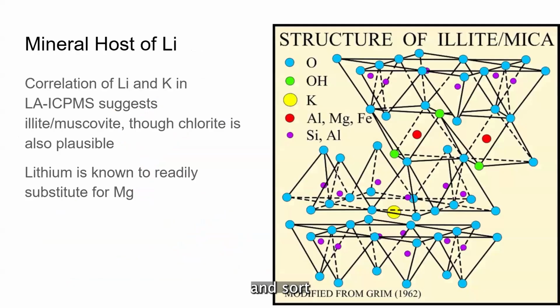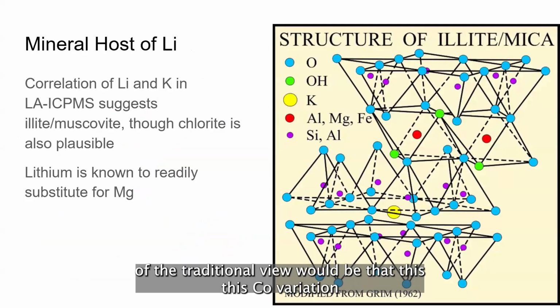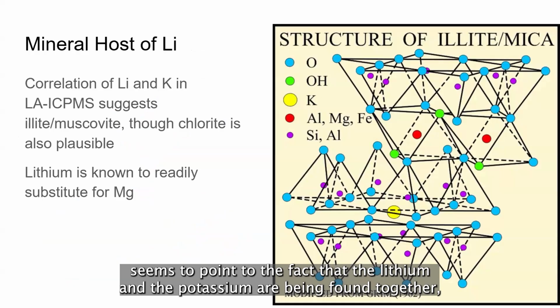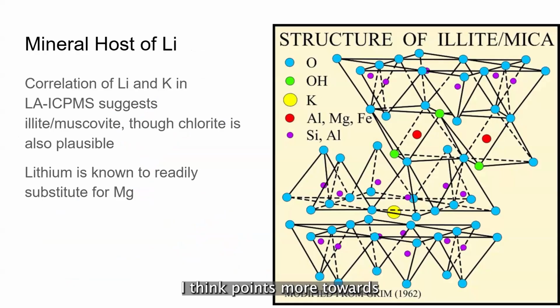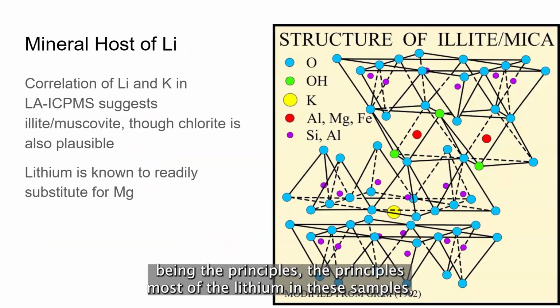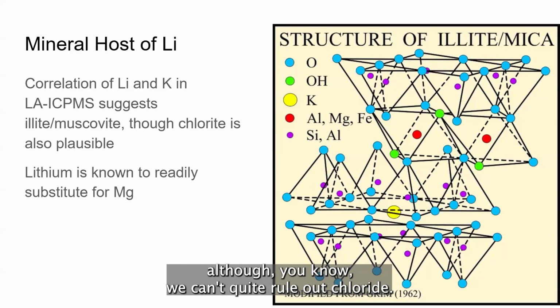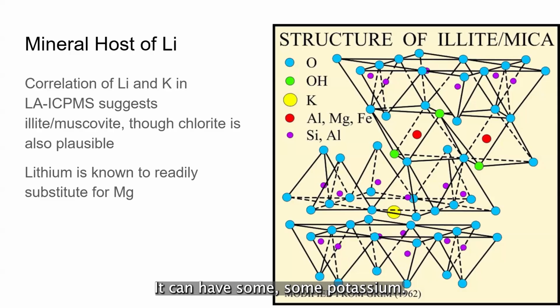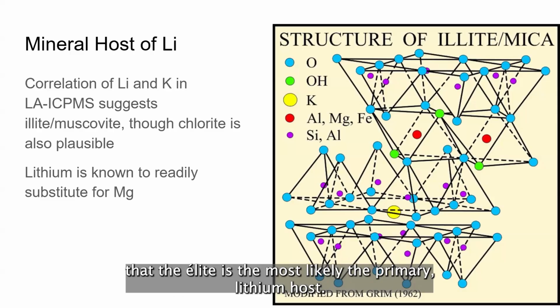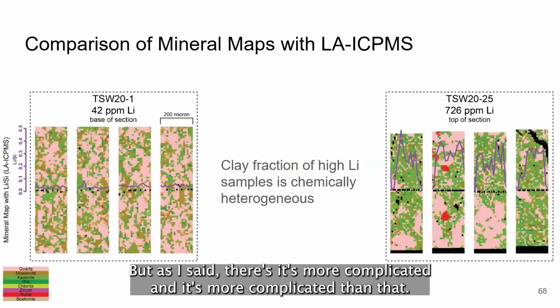And the traditional view would be that this covariation, the fact that the lithium and the potassium are being found together, I think points more towards illite or muscovite being the principal host of the lithium in these samples. Although, we can't quite rule out chlorite. Chlorite can have some potassium, but I think overall, this suggests that the illite is most likely the primary lithium host. But as I said, it's more complicated than that.